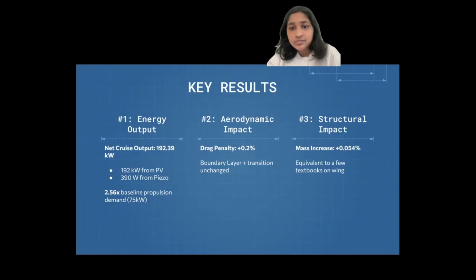In aerodynamic terms, that's almost negligible, comparable to adding an ultra-thin coat of paint. If the drag penalty had crossed even 1%, the system would have lost more energy through fuel burn than it generated. Instead, the aerodynamics remain nearly identical to the baseline wing. Structurally, the mass increase is only 0.054%, equivalent to adding just a few textbooks to a commercial wing. This confirms that the ultra-thin material selection achieved its purpose: meaningful energy harvesting at almost no structural cost.